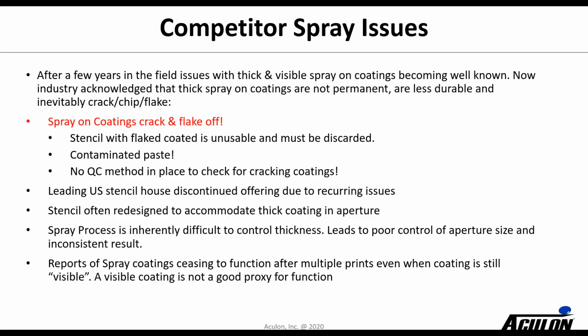And so on to the next page to detail some of the reasons why you would want to focus on utilizing NanoClear and consider staying away from some of the thicker competitive coatings. After a few years of experience with these thicker nano coatings for stencils, it's become pretty well apparent that they're not as durable as everyone thought they were initially. Most customers are seeing pretty significant cracking and chipping and flaking of the thicker spray coatings. And this is a problem for several reasons. Aside from the fact that it's not as durable as everyone thought, these coatings coming off can contaminate the paste. Once the stencil coating is damaged, they need to be discarded. In fact, the leading U.S. stencil houses have discontinued offering these because of the recurring issues.